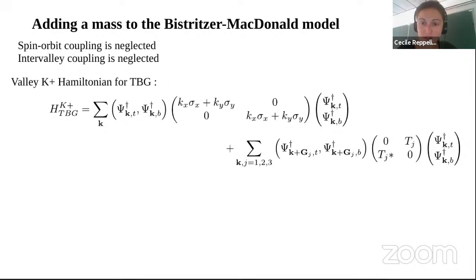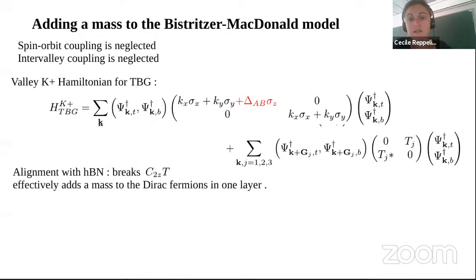I didn't mention that, typically, since we have rotated layers, it would make sense to add a rotation to one of these Dirac dispersions. You can, in fact, neglect it, as was explained last week. Now, to this plain Bistritzer-MacDonald model, I'm going to add a term which breaks C2T symmetry. And that term comes from the alignment with the hexagonal boron nitride substrate.